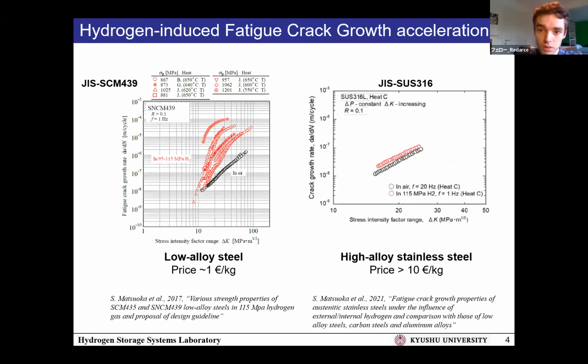The other one is a fatigue crack growth acceleration, so it's very well tied with the loss of ductility. But we can see that in the materials used nowadays to counteract hydrogen embrittlement, there is not that much difference in the crack growth rate while it's being tested in air, here the black line, or in high pressure hydrogen environments, here the red line. So these are quite good results, but they come from very expensive materials.